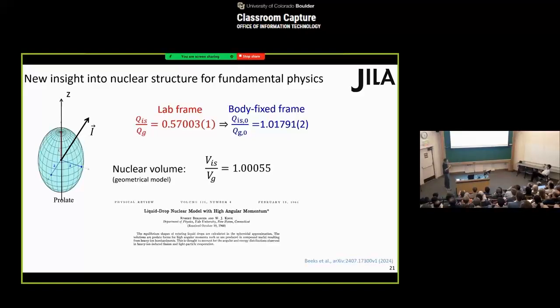And this, combined with some other nuclear physics parameters, we can then use a purely geometrical model to deduce the corresponding nuclear volume in the ground and excited state. Now, people typically assume that in these nuclear transitions, your nucleus looks like an incompressible liquid droplet, where the ground and excited state volume would stay the same. You can see that this is indeed a very good approximation, but we are now at the measurement uncertainty where this approximation starts to break down.